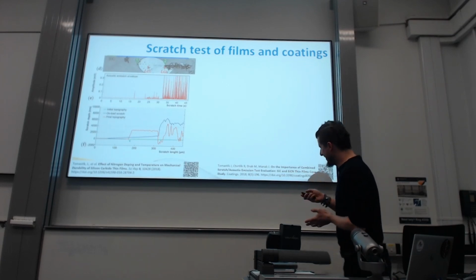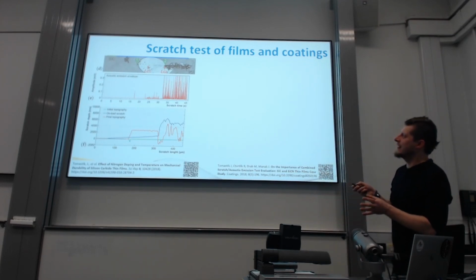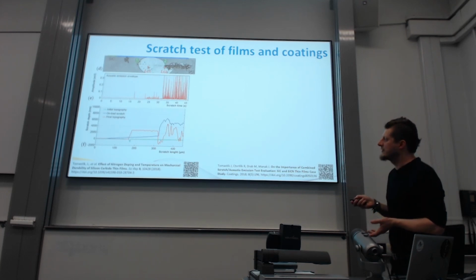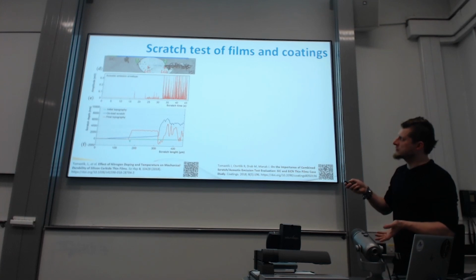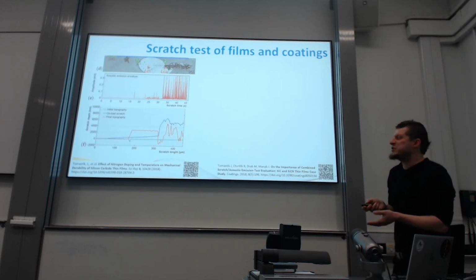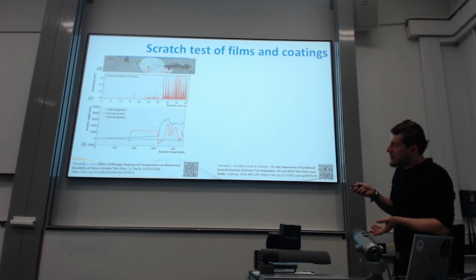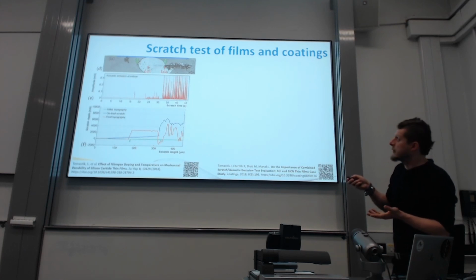It's my fairy tale. Because from microscopic observation or depth change, you would have bad information. Let's see what happened. We have a progressively loaded scratch track, and let's see the depth change. In the first topography scan, we have a nice surface, and there is some debris. Okay, so let's go to the scratch under increasing load, but not so much here. I would expect something here, but just a little bump. But in acoustic emission, there's a signal. A little later, in the microscopic image, there is something, apparently surface cracking, but no depth change, yet acoustic emission hears it.